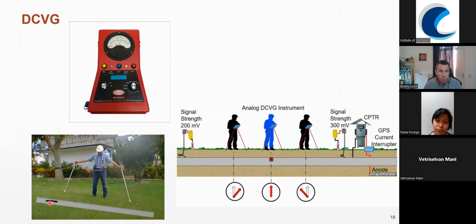So the first step is that you walk in parallel. Both reference electrodes are moved in parallel to the pipeline, as shown in this picture. And once you're getting closer to the defect, you will see that the dial is moving. Then when you are coming on top of the defect, you are not going to see any movement. And then when you are passing by, the dial will move in the opposite direction. In that situation, you have identified the location of a defect.